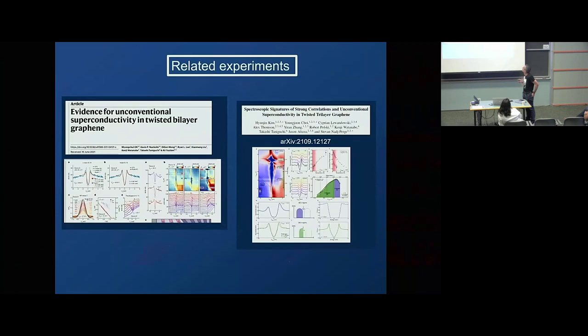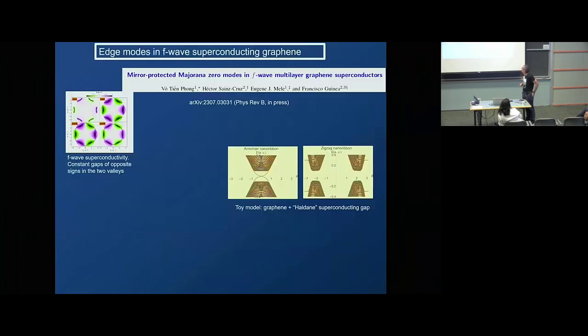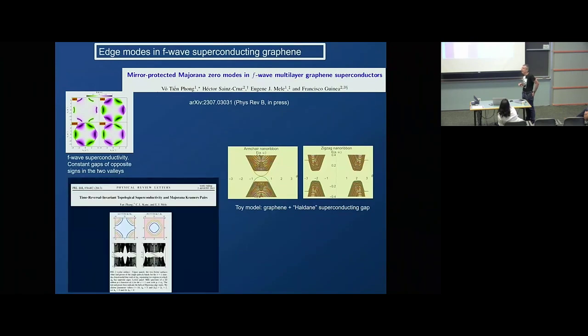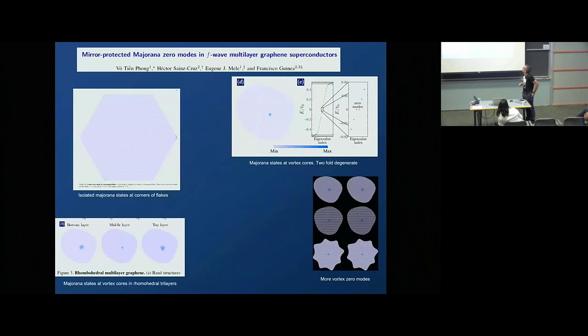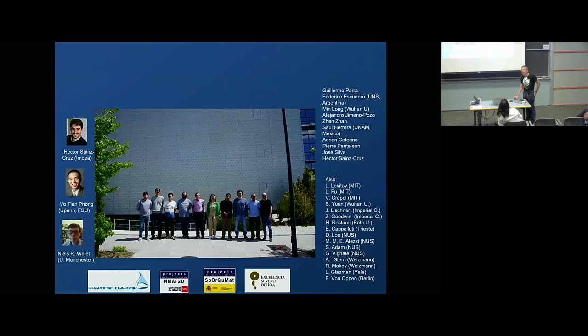And so these are the experiments I was mentioning to you, STM experiments, according to which you see peaks in the contact regime. Last but not least, let me mention that if you have this kind of f-wave superconductivity, you can also have Majoranas, not very protected, because of the symmetries of the system. If you have an edge where an electron comes from one valley and is scattered back into the other valley, it's like what I mentioned to you that the tip can do. You have intervalley scattering and you have Majoranas, which can be sitting at corners of a flake and things like that. That's it. Thanks a lot for your attention.